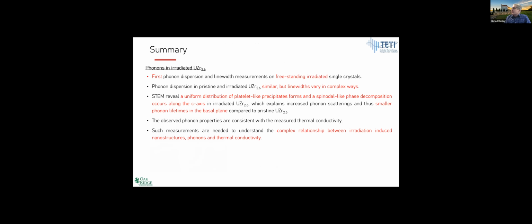And so, the summary. These were the first phonon dispersion measurements in freestanding irradiated crystals. This is because it's basically difficult to do anyway, and so it hasn't been done in freestanding crystals. The phonon dispersion in pristine and irradiated UZr2.6 are similar, but the line widths vary in complex ways. And the STEM gives you some idea of why these things are happening, although I think more modeling is needed. We have some modeling, but it's really difficult to explain everything.